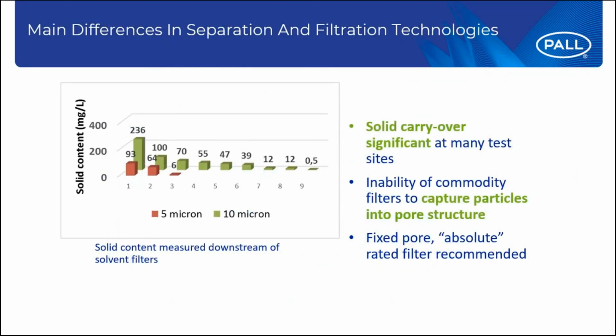We have also measured solid contamination downstream of a nominal filter and downstream of absolute filters, and when we bring that chart with the data together, we see that solid carryover can be significant at many sites, although the filters have been defined as a 5 micron or a 10 micron. This definition or specification of the filter alone is clearly not enough. You also need to specify the performance of your filters, the rating of your filters. It's very important for the right filter to be installed.